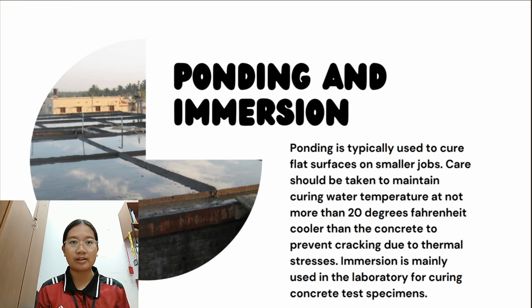First is ponding and immersion. Ponding is typically used to cure flat surfaces on smaller jobs. Care should be taken to maintain the curing water temperature at not more than 20 degrees Fahrenheit cooler than the concrete to prevent cracking due to thermal stress. Immersion is mainly used in the laboratory for curing concrete test specimens.